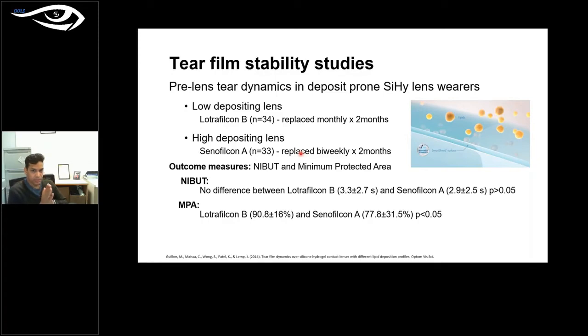What they looked into is the tear breakup time, and also the minimum protected area. If the minimum protected area, meaning it's wettable, is greater, that means the surface is doing better. As you can see, in terms of breakup time, there was not a big difference between Lotrafilcon B and Senofilcon A lenses. However, when it comes to the protected area, Lotrafilcon B outperformed Senofilcon A. So again, in this case, we have a coating here, but we don't have a coating here.